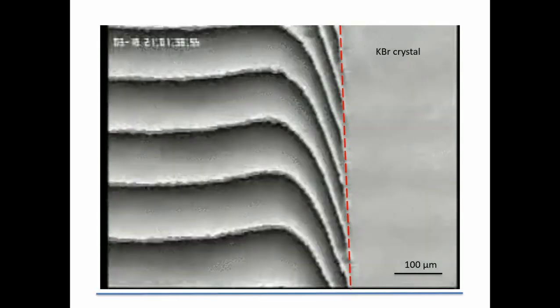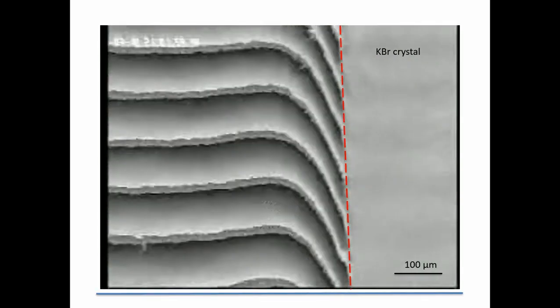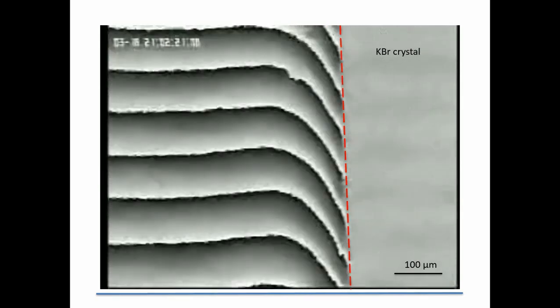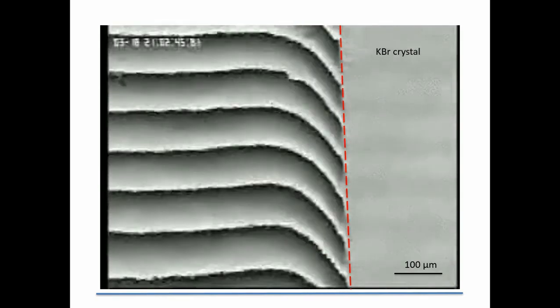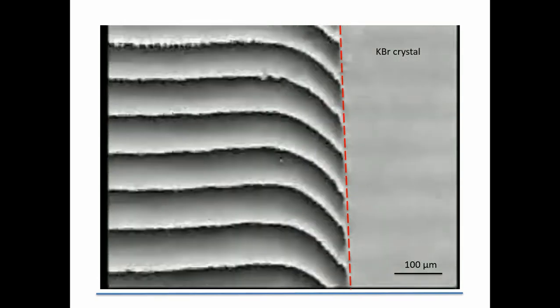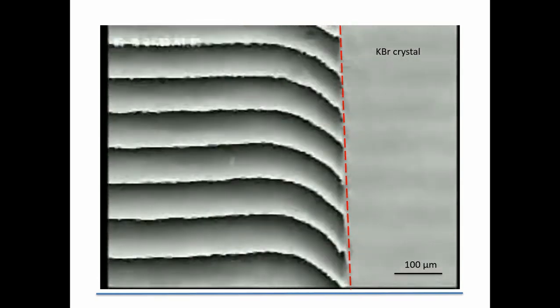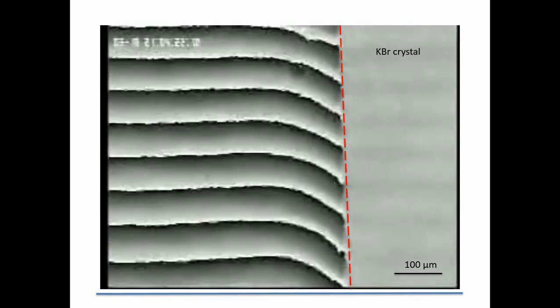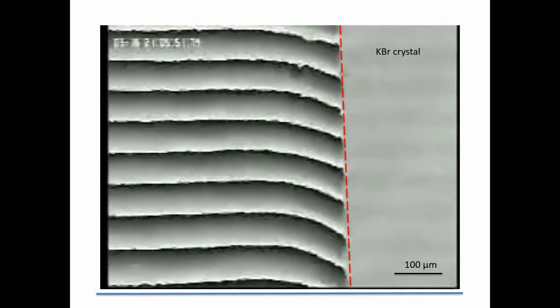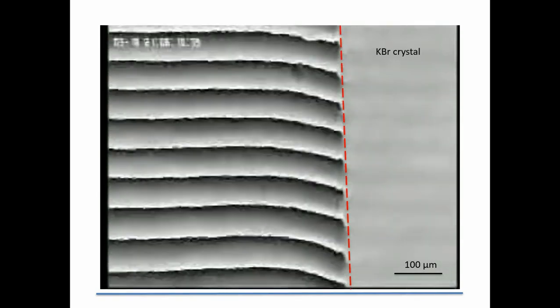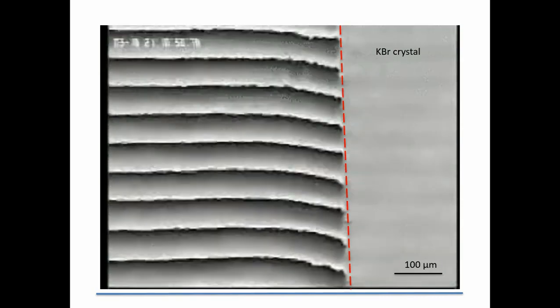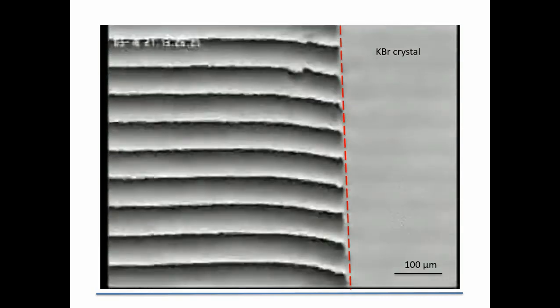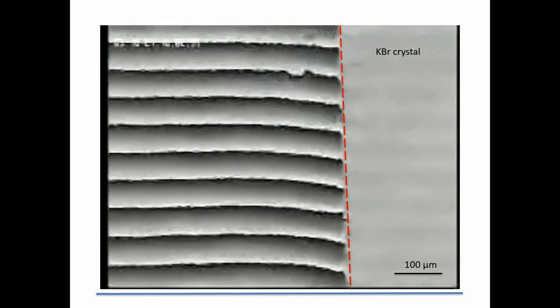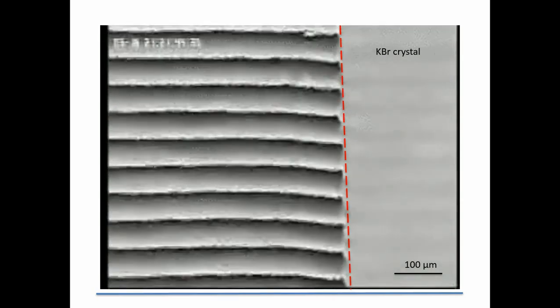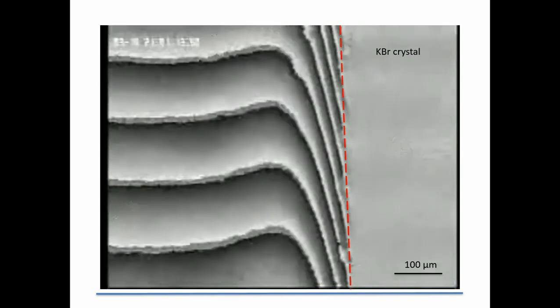Have a look at the way these lines are representing the refractive index of the solution, so it's the solution composition. Don't worry about the lines, except the distance indicates a change in composition. As soon as that fluid touched the surface, there was a huge compositional change at the surface. Out there in the bulk, it takes longer to change. As time goes by, I've put the lines in there to the right. That's the crystal on the right-hand side.